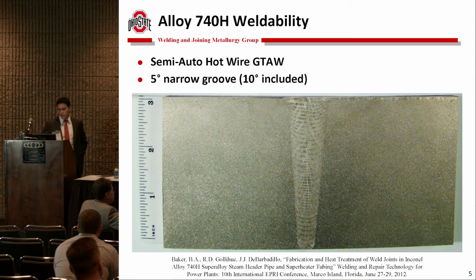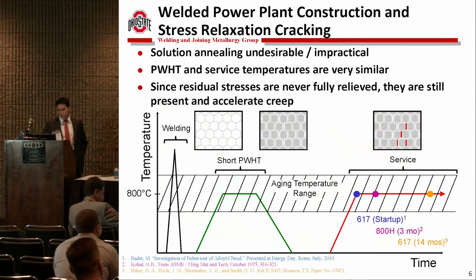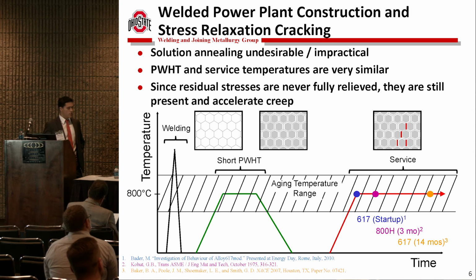The problem, though, is that the post-weld heat treatment that is desired is simply an aging treatment. It would be ideal to get away with only an aging treatment and then put this thing in service. But when you're only aging, you're not relieving very much stress because you're forming all this gamma prime, and so you're setting yourself up for a relaxation cracking problem. As I mentioned, we would rather not anneal and then age these main header pipes, because this is for power plant construction. The post-weld heat treatment temperature and the service temperature are almost exactly the same, so you're never going to fully relieve any residual stress because you have all this gamma prime precipitation.